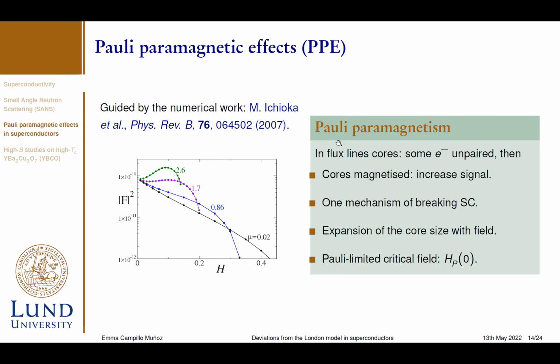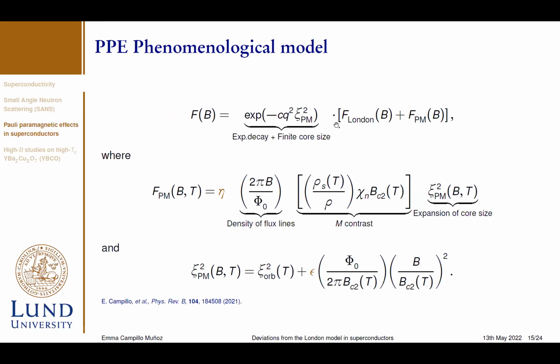Following these requirements to develop our model, we can start from the London model expression that we saw before. We still have our Gaussian cutoff to have this decay along field, but we included a paramagnetic term in this expression. In this paramagnetic term, we have to include the density of the flux lines present in the material depending on the magnetic field, the extra magnetization that is created, and also the expansion of the cores, which depends on the temperature and the field that we are applying. The remarkable thing about this model is that only two fitting parameters are needed to describe the behavior of Pauli-limited superconductors.